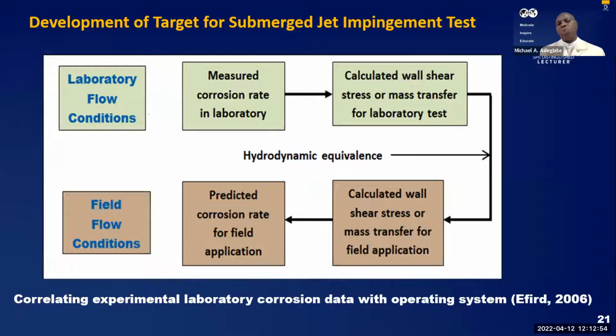So in order to really simulate field conditions wherein we have a shear stress in excess of about 200 newtons per meter squared. What we have typical is less than about 70. That's what the previous tests have indicated. And then we need to get closer to what the flow conditions is like.